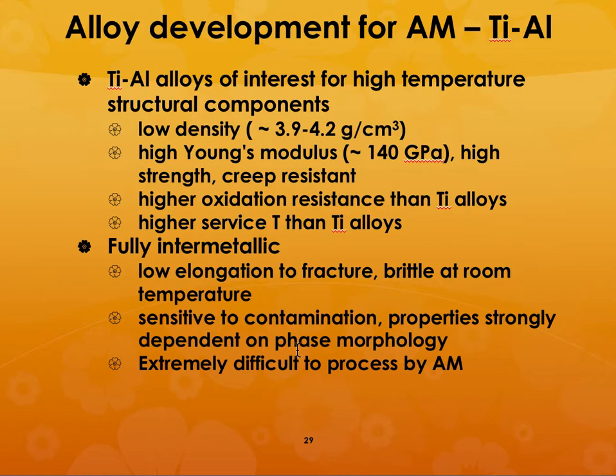So why are we interested in an intermetallic alloy such as titanium aluminide? First of all, it is because it has got very low density, extremely high Young's modulus, high strength, and it is creep resistant. And most importantly, it is more oxidation resistant than titanium alloys. Because of that, it has higher service temperature than standard titanium alloys.